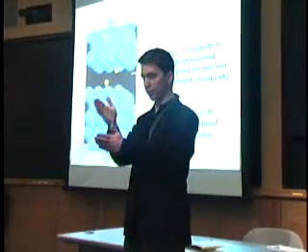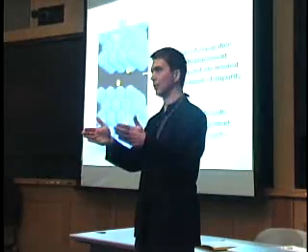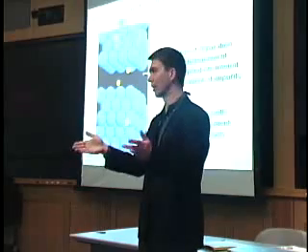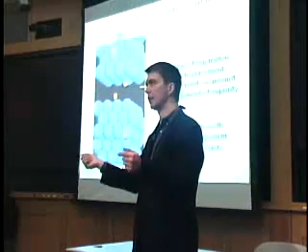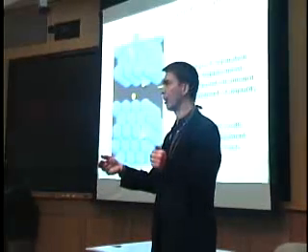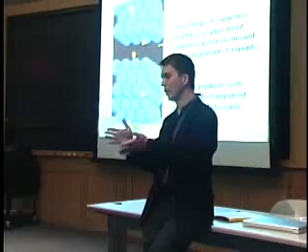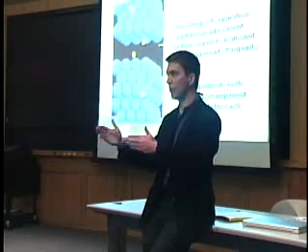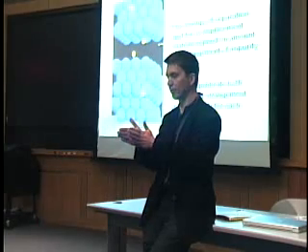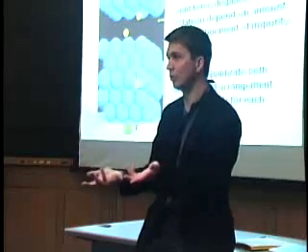You would define a plane where you open up the slab and you pull, you move the two slabs farther and farther apart. So it's like you're opening a crack. You keep track of the energy, and the derivative of that is, of course, the force required to separate the slab. But think of the problem now if you want to do that with an impurity. You have to now equilibrate the impurity at every separation of the slab. So you pull the crack open a little more, and you now have to figure out what happens to that impurity there.